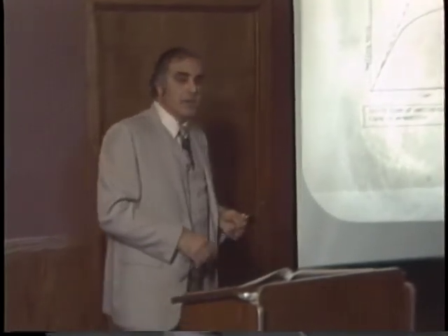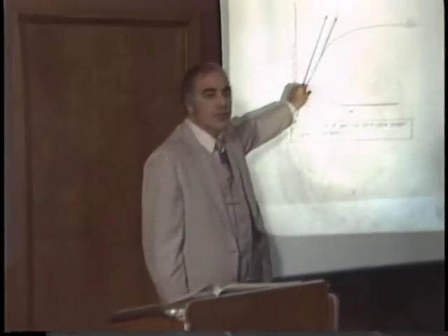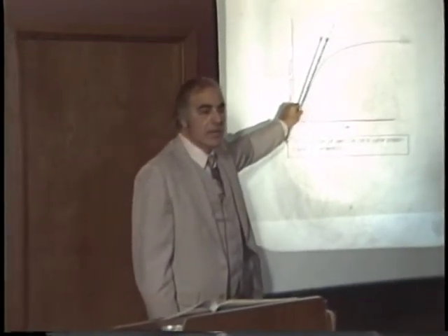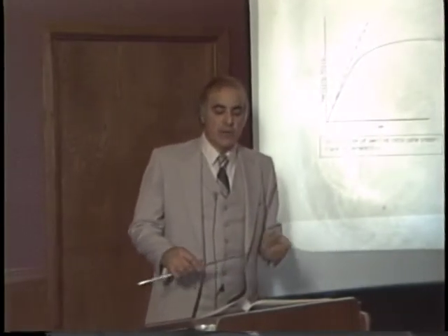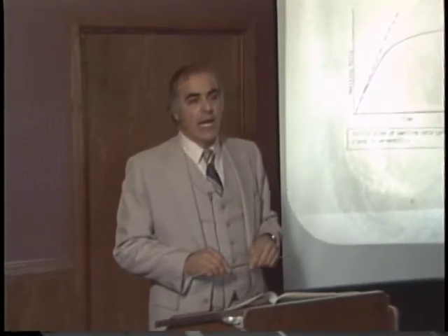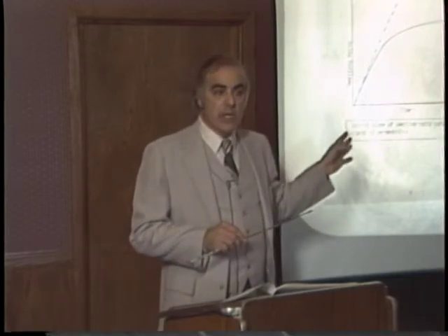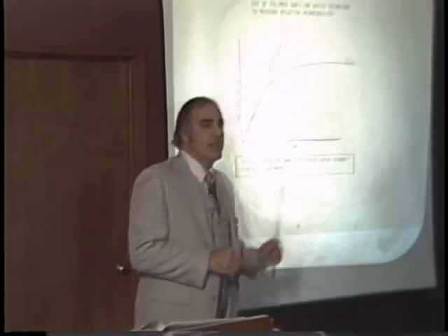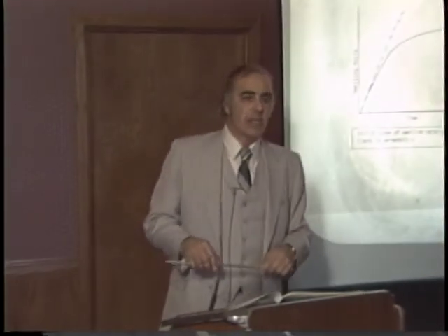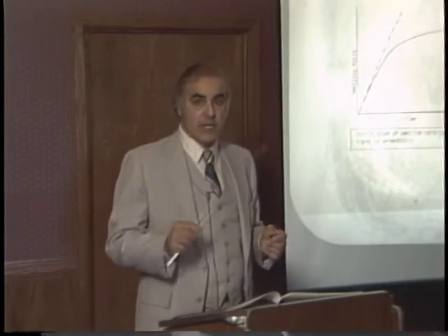Could I have the next slide, please? This is typical of the kind of curve that we get. Now, we found that if we take the initial slope, tangent to that curve, we come up with a value that is directly proportional to the actual permeability coefficient for that liner for the given migrant that we're looking at. And this distance here, incidentally, is somewhat proportional to the solubility characteristics of that particular liner. Can I have the next slide?